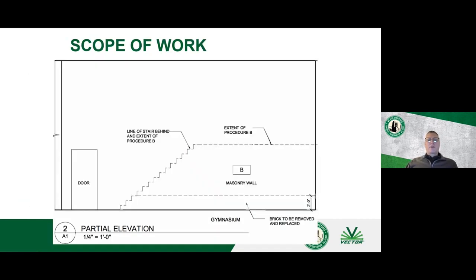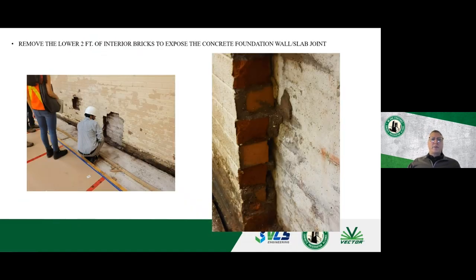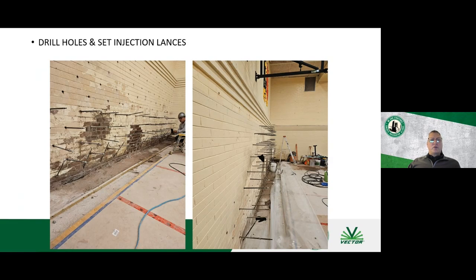So they're having water intrusion behind this masonry wall. They're removing part of the bricks here so you can get to the concrete that's behind this masonry wall. They're having water push through. It's coming out through the bottom between the slab and the wall itself, causing a lot of problems for this school. So our team went in, drilled holes at intervals, and installed these lances.